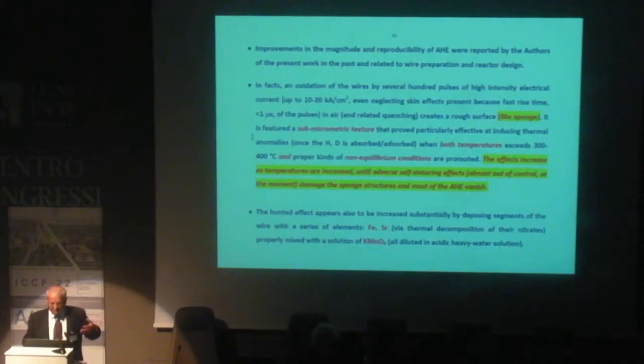To make a sponge, before you use the very high pulse, up to 10-20,000 ampere per square centimeter, repeated several hundred times. But now use more simple, just for check. Anyway, using the pulse is the best way, even if time consuming.